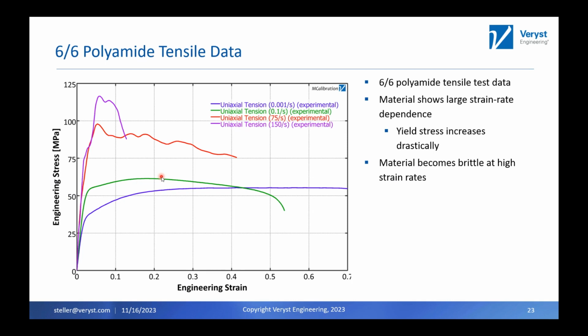So if you're not aware, almost all materials, and in particular polymer materials, are viscoelastic, viscoplastic, and that means that they have rate dependence. And I could talk for hours about where that rate dependence comes from, what it means, where you might expect it. But I think this is a good example on some nylon data that we tested. All of these are done at 3 different rates. This blue is done at 1 times 10 to the minus third strain per second, and this purple is up at 150 strain per second.